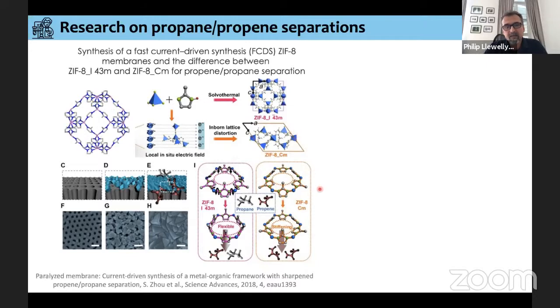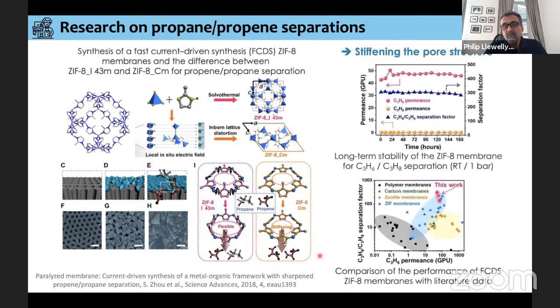And the idea is given here. With a normal ZIF-8 material, there would be very little separation power. But if they can stiffen the material inside the membrane, then maybe they can get very good separation properties. This is what we're going to see on the right-hand side. This is a membrane. We can see the permeance of the propene and the propane, and the difference here is quite large. The separation factor is also here in blue, and it's also quite nice. They then compared the performance with other types of membrane materials, and they suggested this work is quite good.